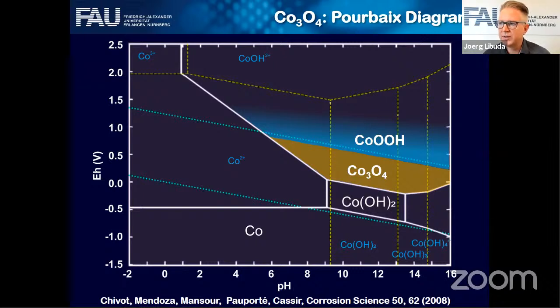So it would be good to make sure that when you do this transfer, you're somewhere in the stability region, and then maybe you can explore what happens if you're leaving that region. However, I want to point out that this is, of course, a bulk stability diagram. So it doesn't mean that there's no solubility in the electrolyte. There will still be certain solubility, so you may lose ions.